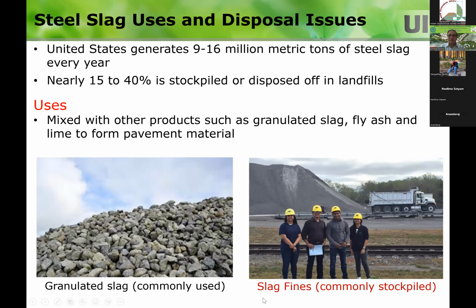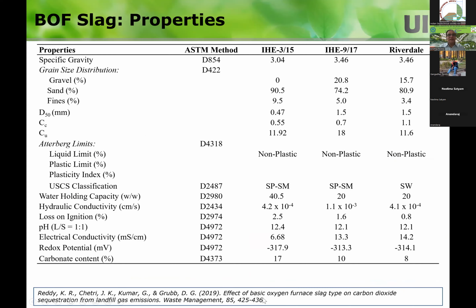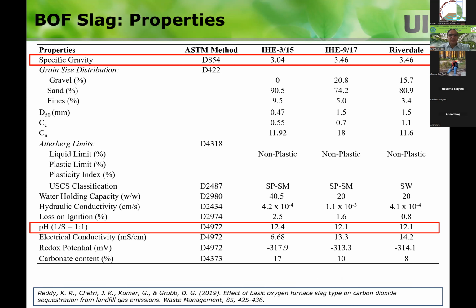So we wanted to look at this slag fines, and then characterize what the properties of the BOF slag are. Basic oxygen furnace, BOF, is that one. So you need to be very clear with what type of steel slag you're using. Specific gravity is obviously very high, and the pH is very high. Those are the distinct properties of the slag.